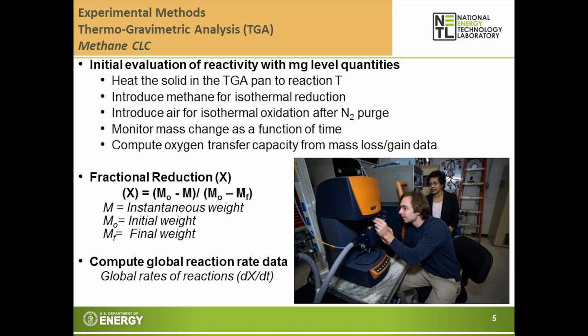Now, we can use milligram level quantities for this technique. We place the solid in the TGA pan and then heat the solid to the reaction temperature, and then we introduce the fuel gas methane for the isothermal reduction at the reaction temperature, and then we use air for the oxidation. We monitor the mass change as a function of time during these reactions, and using that data, we can compute the oxygen transfer capacity and also the fractional reduction. And using that, we can also compute the global reaction rates data.